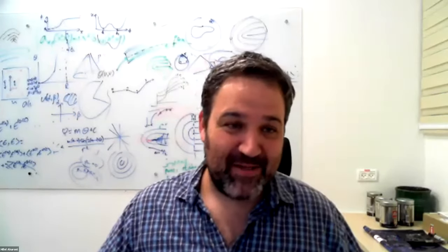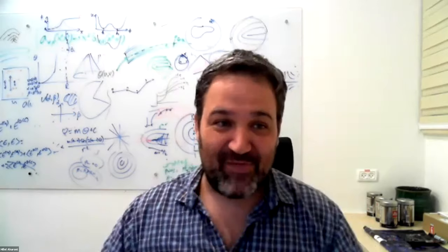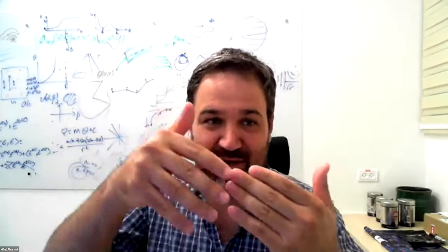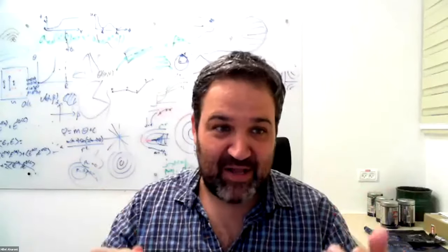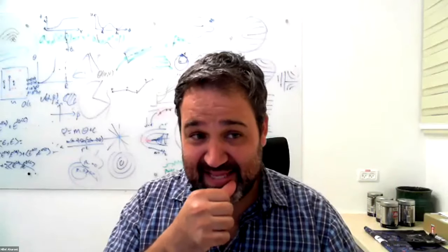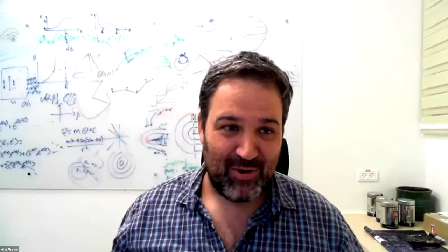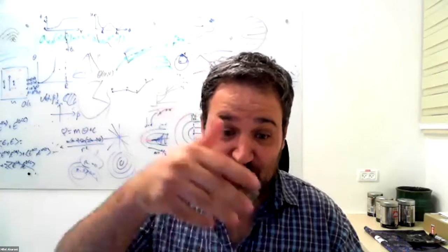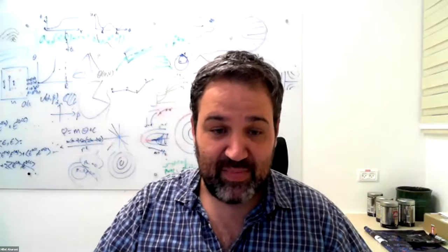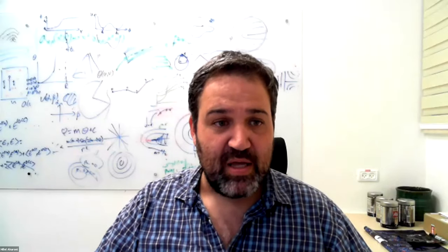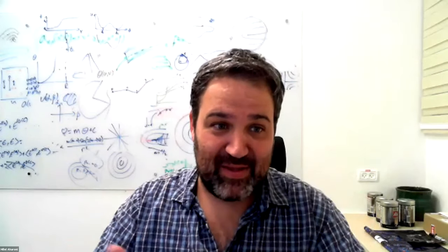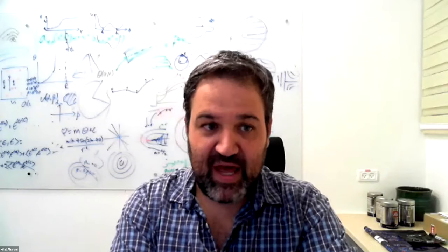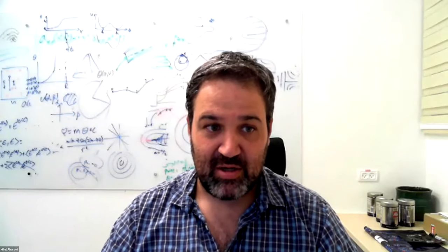Apart from what I already said, there is an assumption that we can imprint any director field that we want into the nematic elastomer, but this is of course not real. We can make channels that change the direction very quickly, but we only have finite surface anchoring, it's weak anchoring, and the nematic director will just not obey. If we try to impose too strong gradients in order to produce strong curvatures, the nematic director will not obey, and we will not have the actual director we want. So there is, of course, a length scale between the elastic constants of the nematic and the surface anchoring. This is the length scale below which we cannot impose the nematic director.